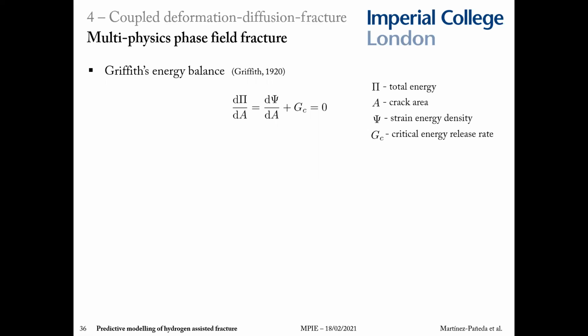So those of you familiar with fracture mechanics will remember that Griffith, one of the fathers of the field, postulated that a crack will grow if the energy released by the solid reaches a critical value, this so-called critical energy release rate or material toughness. This energy balance is a result of considering, in a thermodynamics context, the work required to create two surfaces.